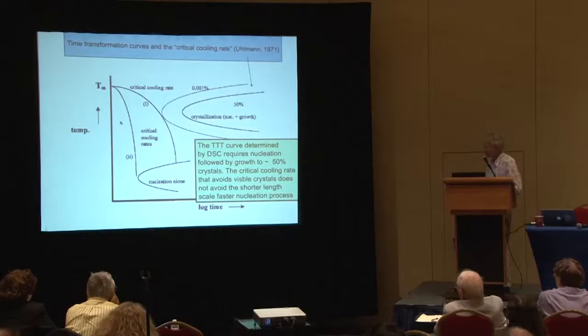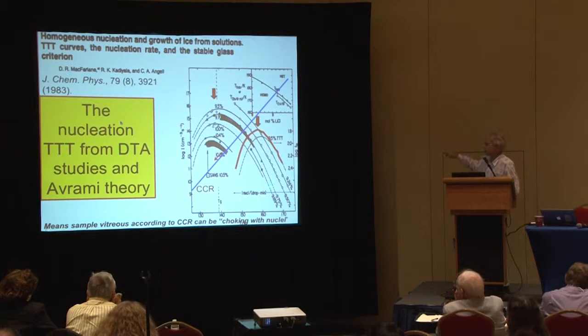So preliminary to that, we'd already wanted to separate out the nucleation from the nucleation plus growth, and we were doing it by theory. And Doug McFarlane with the Avrami theory had deduced that the nucleation curve should be here, and the TTT curve, which we determined by the isothermal calorimetry, was this one. And you see that there's a difference in temperature between the two, and there's a difference in time scale.